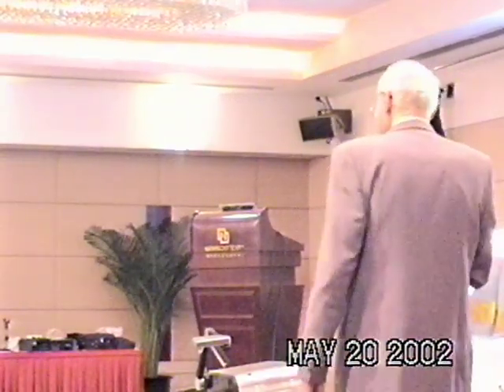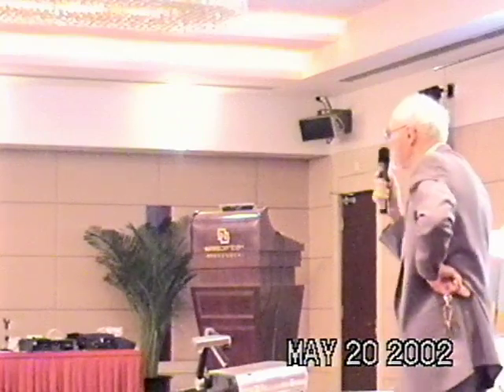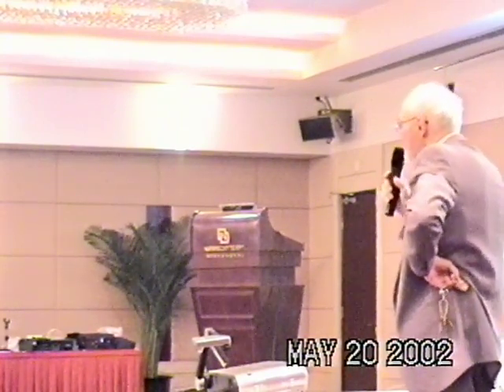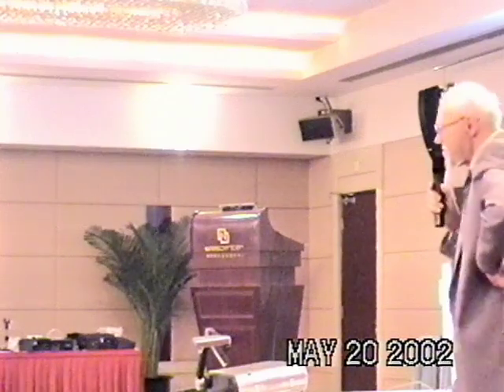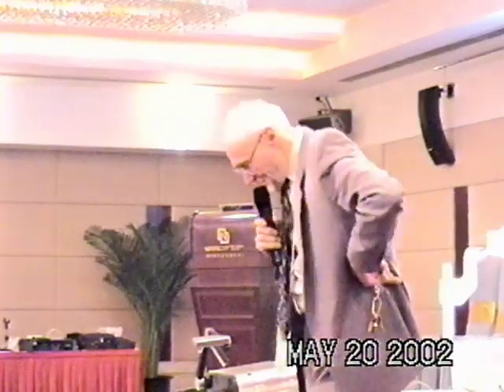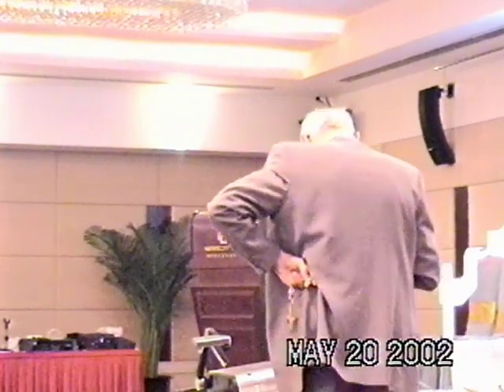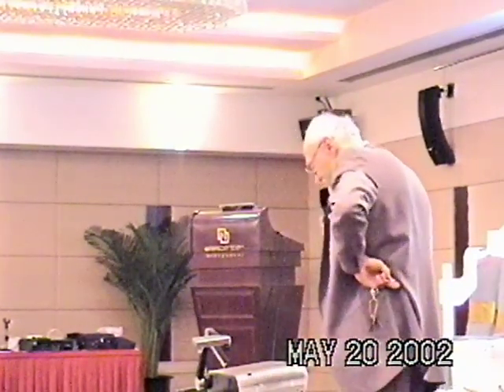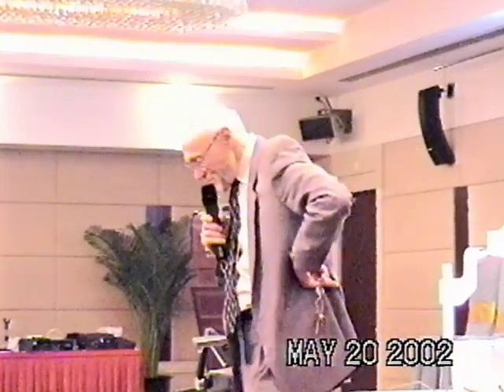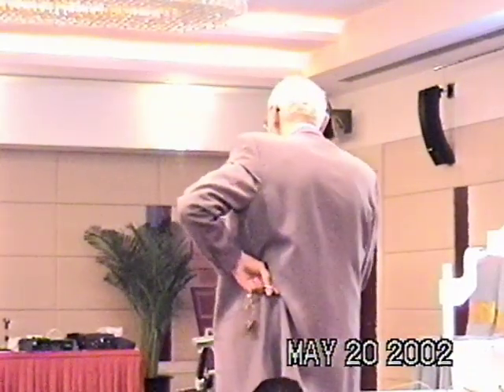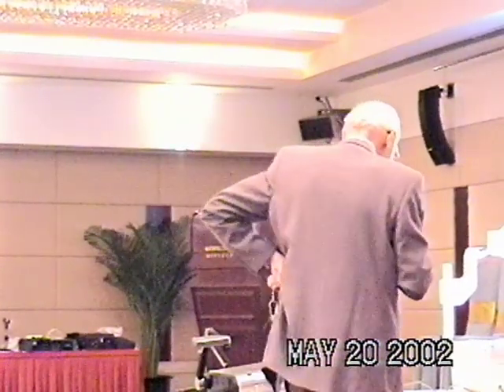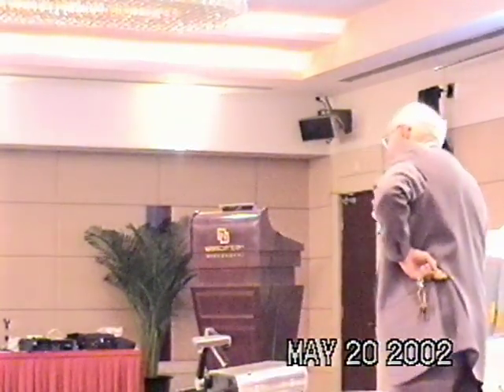Yes, please. I know that you check to make sure the hydrogen reaction is not occurring as far as lithium hydride coming off by looking for and not finding Li8. But in the United States, the normal ratio of atomic weights for lithium is crazy because the Atomic Energy Commission, back when it existed, dumped so much lithium that had been separated out into the commercial market. Did you check before and after on these lithium ratios?